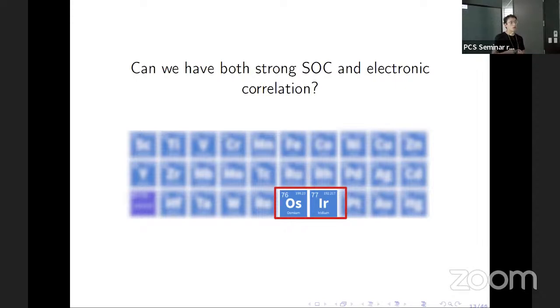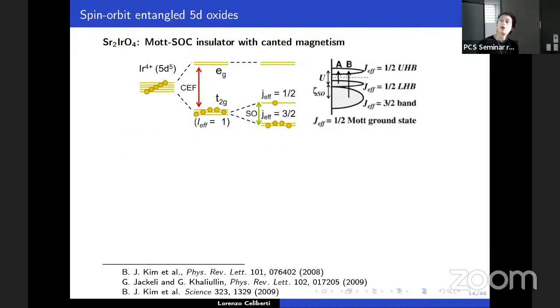And also, I will come with the next slide to see one material in particular, which was the first one in this class of compounds, which is strontium iridate. This material is an insulator experimentally, but from the band picture, it comes out like a metal. So why is it like that? If you try to add the Hubbard correction, you need an extremely large, unphysical value of U to open a gap. So this doesn't work. But if we introduce spin-orbit coupling, then with a U of 1 electron volt, you open the gap, and you manage to reproduce the physical properties of this material. So this has also been called a spin-orbit coupled Mott insulator. This was the first material we found in this class of compounds.